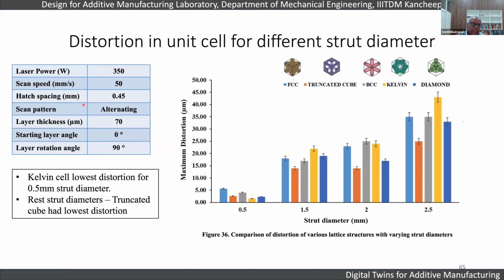So these are the process parameters that we have used, and we found the Kelvin cell typically has the lowest distortion because it has a higher surface area. Whereas for the rest of the strut diameters, for example, truncated cube has the lowest distortion. In this maximum distortion graph, you can see Kelvin, the yellow one, had the lowest distortion in most of them, among all in the lowest strut diameter.